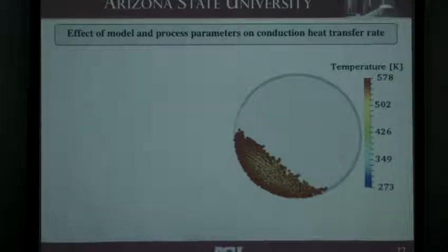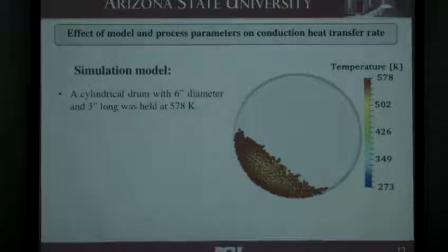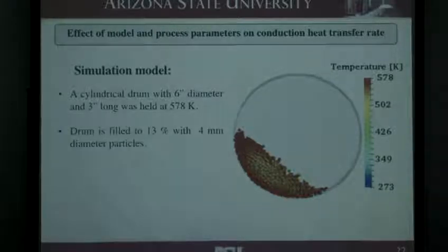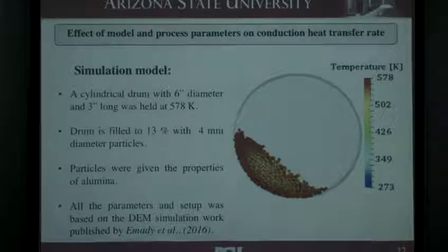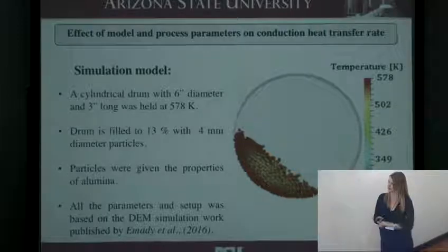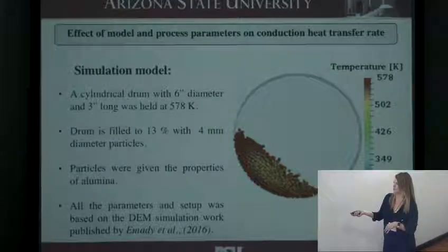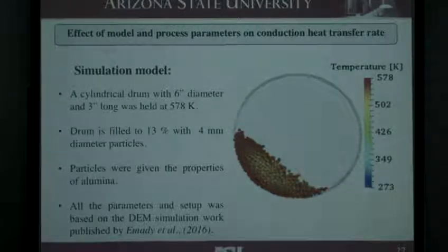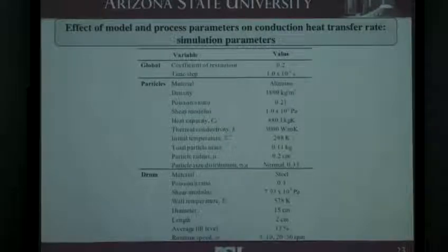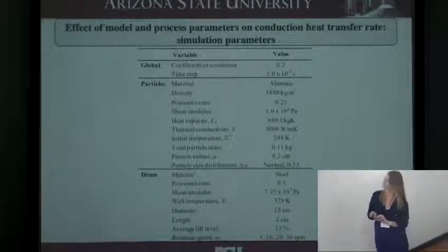To do this study, we used a slightly different system, same geometry, but a little bit of a hotter wall, a couple hundred degrees Kelvin hotter, and we have a 13% fill with 4 millimeter diameter alumina particles. We actually used the simulation information from the paper I published earlier, just because we had that information and we wanted to compare EDEM with this MFIX heat transfer. So these are the model parameters, the simulation parameters.